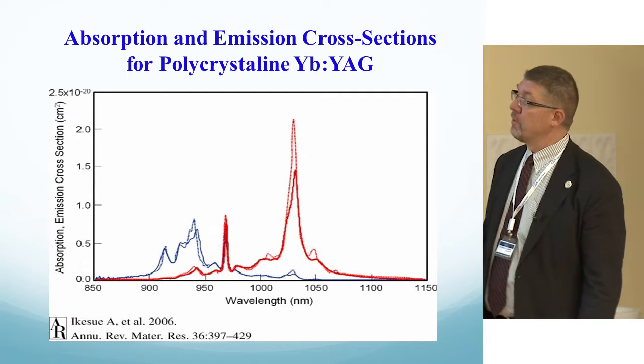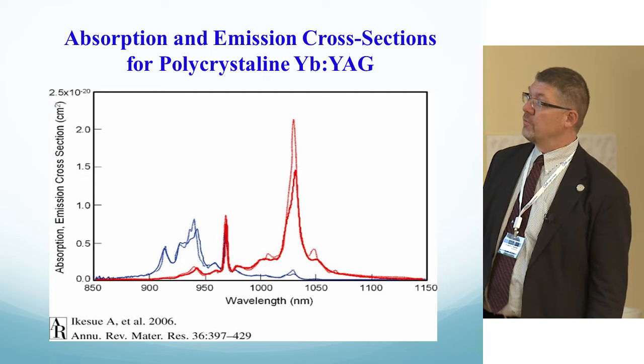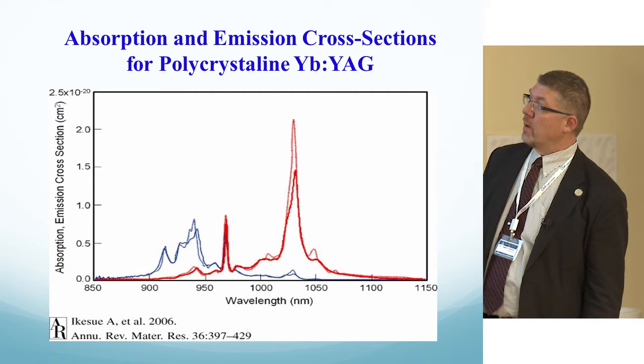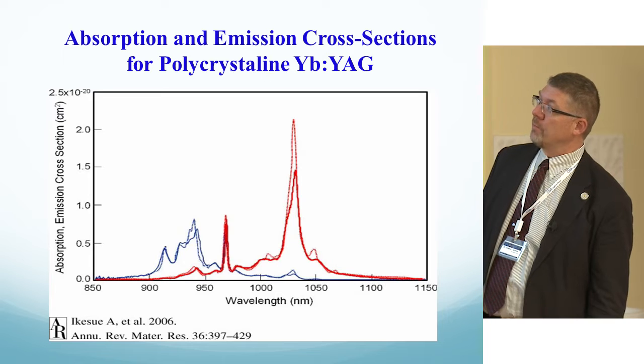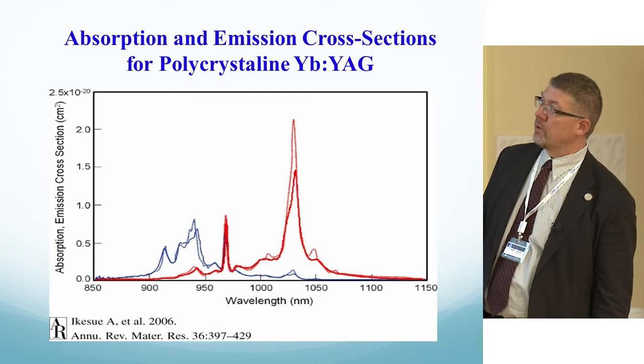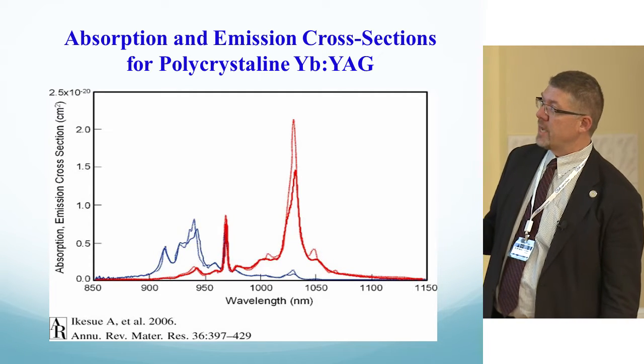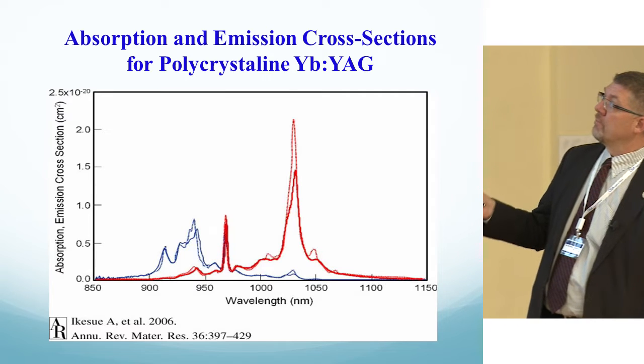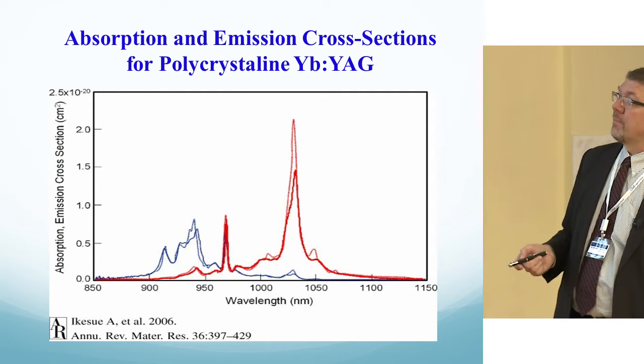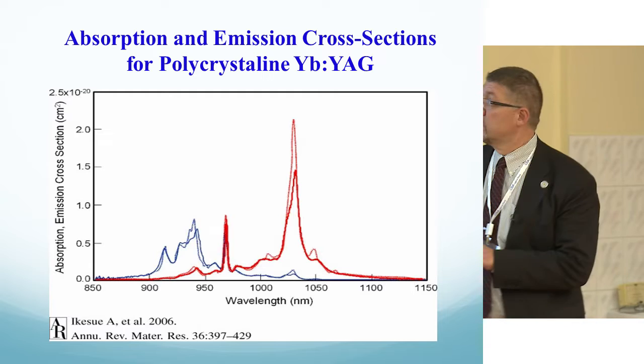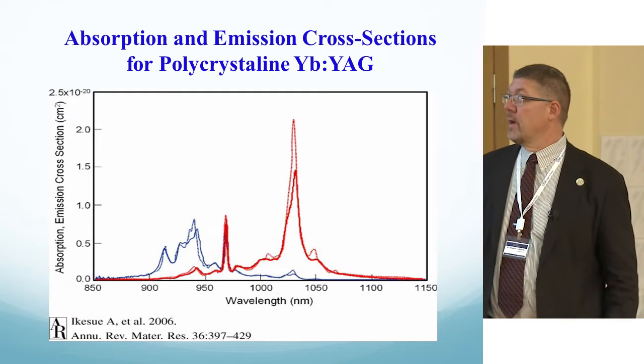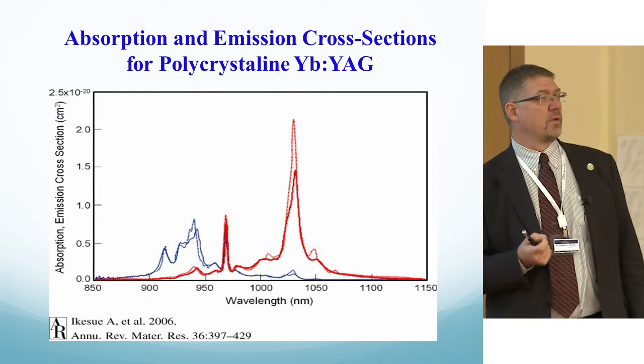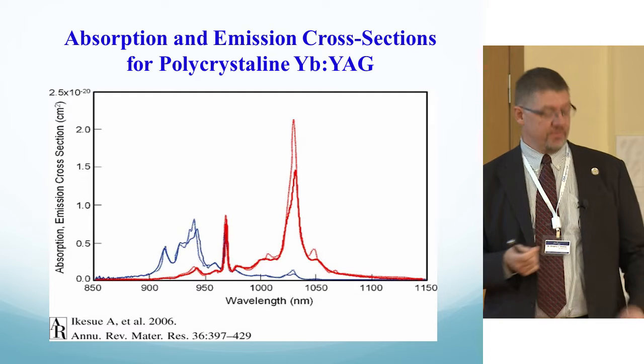I saw some papers and posters earlier today where students were measuring this. So you pump right here at about 940, where the peak of the absorption cross-section is for ytterbium. You see the absorption tailing down here. Here's the peak of your emission coming up top here. The thing that you note is that absorption and emission overlap down here, so you don't have a true four-level laser. It's actually a quasi three-level laser.